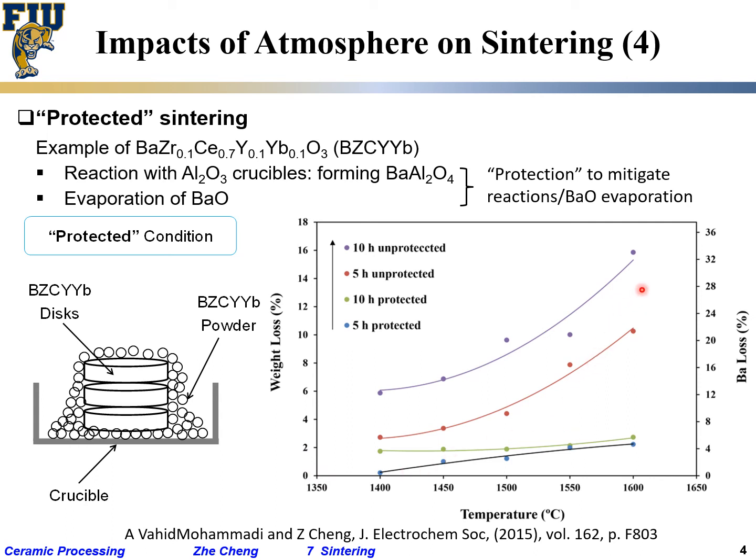But what we find, if we don't do this protection, 5-hour, 10-hour, we are having significant weight loss, meaning significant barium loss. And of course, naturally, the higher the temperature, the higher the loss. The longer the time, the more the loss. Makes sense, right?